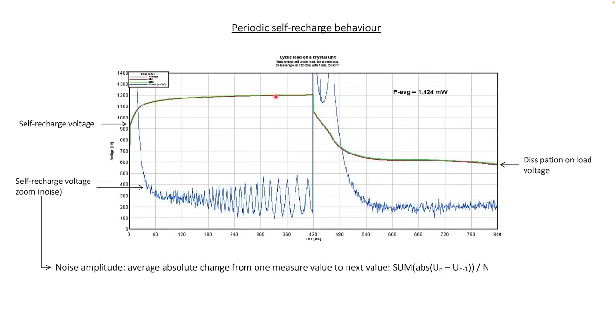In addition to the voltage run, also the noise was registered again, because we had this interesting observation related to noise before. So we ask, how does the noise behave during a self-recharge phase? And we saw that the noise level first dropped down and then it got into an oscillating mode for a few seconds, where it gets higher and lower and higher and lower. And this again is such a unique behavior which demands further research how this can be explained, which is usually not seen in conventional energy converters.